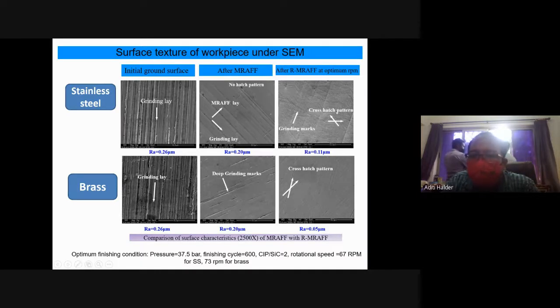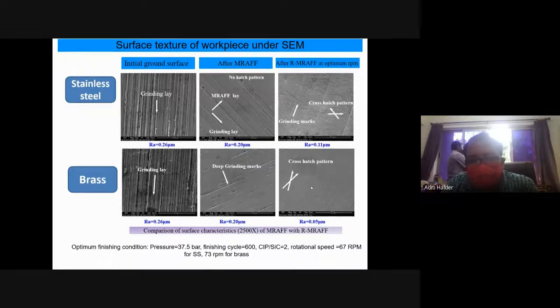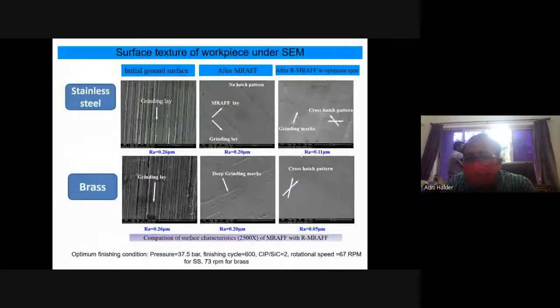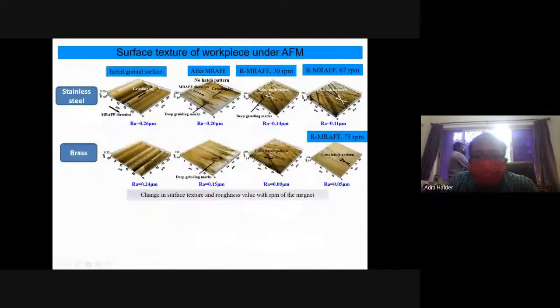This cross hatch pattern helps in oil retention if you are polishing a cylinder. For polishing a cylinder, it helps in oil retention and reduction of friction. So these are the cross hatch patterns, and we found around 50 nanometer surface finish on the workpiece surface. From 240 nanometer, we got 50 nanometer on the brass workpiece. These are the AFM images of the grinding marks here. This is the MRAFF process, and this is the R-MRAFF process, with its cross hatch pattern. With a higher RPM of 67 RPM, we got a very good surface finish here.